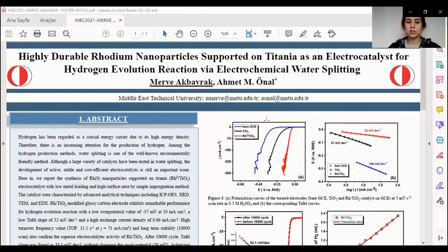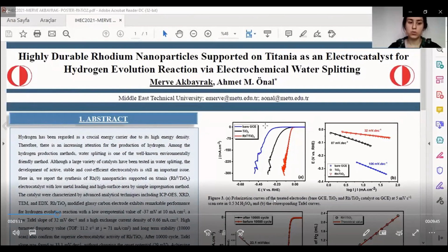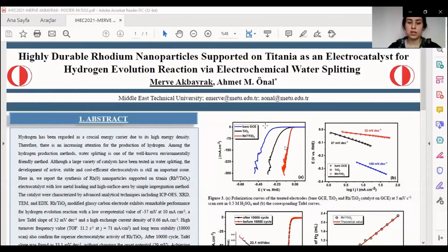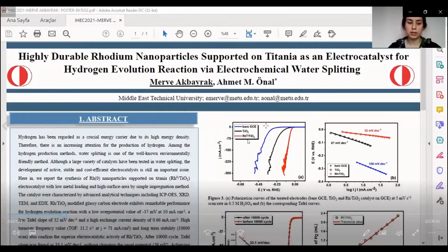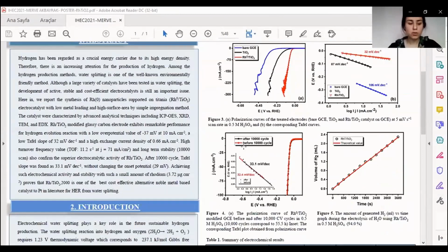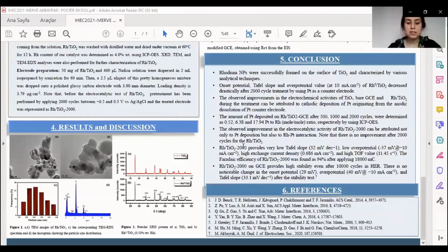The obtained catalyst was attached to the surface of a glassy carbon electrode drop-wise. For all tests, the rhodium amount on the glassy carbon electrode was kept constant at 3.79 microgram per centimeter square. For all electrochemical studies, a three-electrode system was used. Modified glassy carbon electrode, silver chloride, and platinum wire were used as the working, reference, and counter electrodes respectively. Transmission electron microscopy analysis was performed to investigate the size of rhodium nanoparticles. As seen in figure 1A and B, highly dispersed rhodium nanoparticles with a 2.54 nanometer mean particle size were formed on the titania.